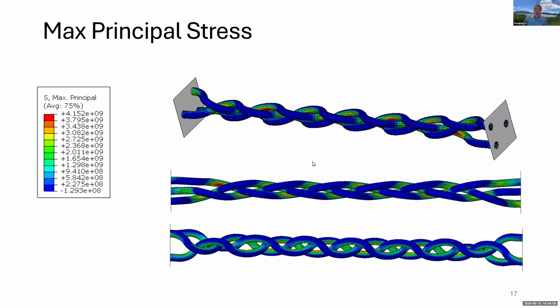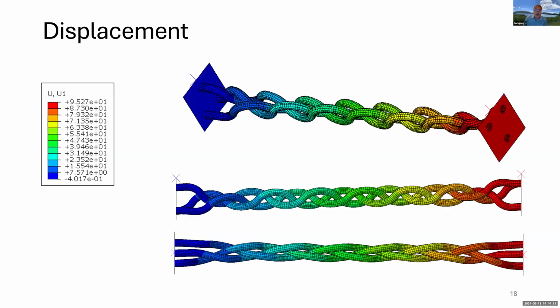And here is the maximum principal stress. Of course, we have not done the straight fibers, so we cannot compare with them. But my expectation is that the principal stress for the braided fiber bundles will be lower than for the straight fibers. And this is the displacement. Again, I expect the braided fiber bundle will have a larger displacement so that it will match the smart polymer matrix.